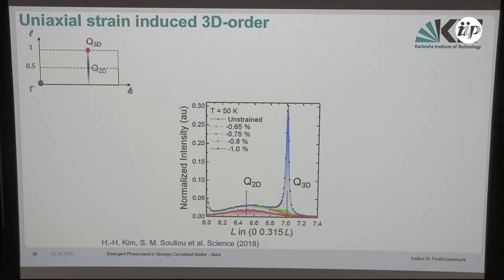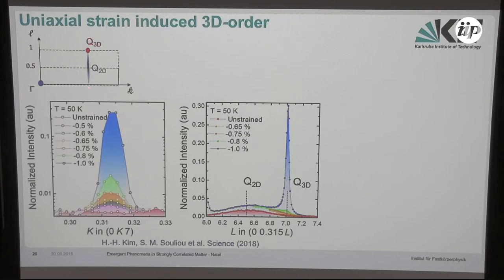And when we apply strain, now we get this peak that appeared at 1% compression. I mean, it starts there at 0.8%, and then it really shoots up at 1% compression. So we were very excited with that. That's a scan along the L direction, and that's a scan along the K direction. What we got here is a very sharp peak, and the in-plane correlation length is of the order of 350 angstroms, which is as long as the longest correlation length that you see in striped-order cuprates. It's really a 3D long-range charge order that we induce.